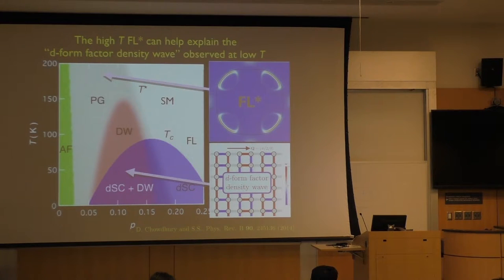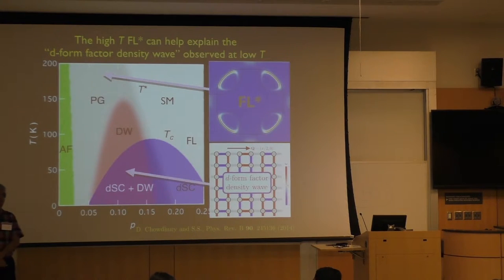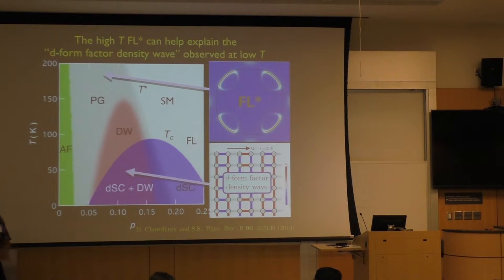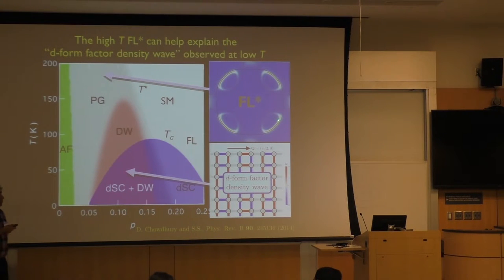But if you look for density modulations — which is not quite Friedel — where you just have a probe measuring the local density, there you're tunneling but you're not really tunneling into those electrons. In some sense you're just measuring the local density. You could possibly see that in QPI. If you do energy-integrated tunneling, just using that as a measure of the local electron density, then the fact that you're tunneling is not that important — you're tunneling at other energies. The Friedel oscillation will then be equally sensitive to the front and the back.